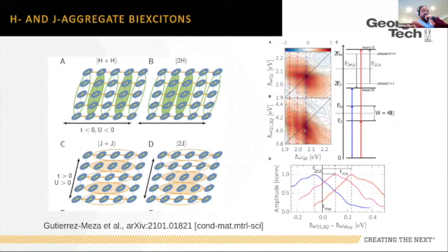So below, that's an attractive binding interaction. Above, it's a repulsive interaction. And I can see that my 0, 0 H aggregate-like thing is bound at something like 60 millielectron volts, but there's a distribution. The peak of the J aggregate exciton has something of the order of 100 and something millielectron volt repulsive energy, and then there's a distribution. And so we can quantify the binding energies. We can now look at this as a function of microstructure, other parameters, and that's something that we're very excited about right now.